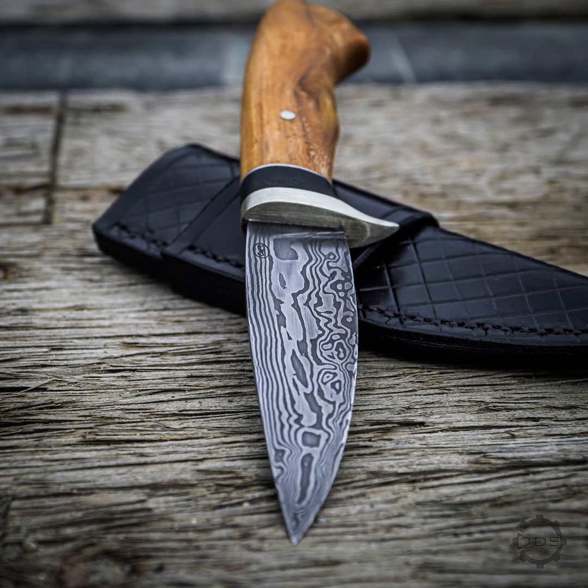So is that what you're gaining by quenching certain portions of the blade, that you get less brittleness through the whole construction of the blade? Right. With your basic high carbon steels, you're able to do a selective heat treat to the blade. You're selecting certain portions of the blade to be hardened and certain portions to be soft and springy. With your super high alloy steels, I have yet to do any testing, but the general consensus is that you can get a superior heat treat by doing an oven heat treat.